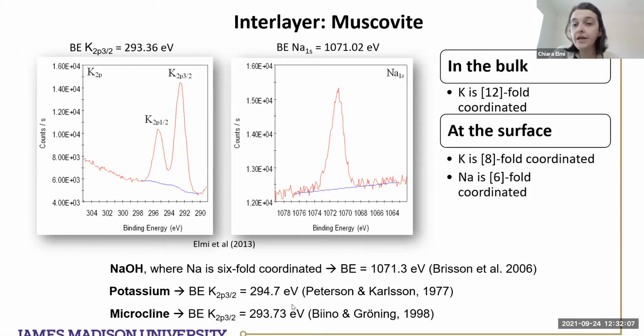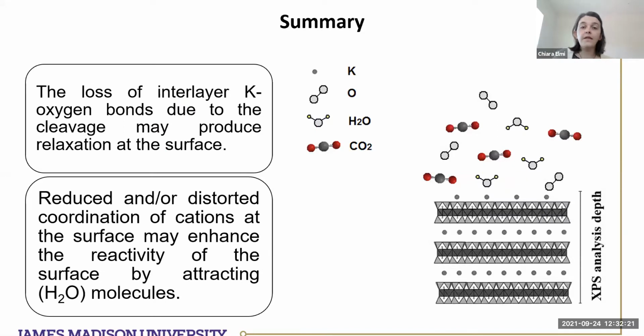That's the binding energy and the coordination that is possible to extrapolate from these peaks. And these peaks define the electron jumps in the XPS. So we relaxed the layer, and we lost some of the potassium on one side of the layer. Most of the potassium oxygen are producing this relaxation, and then this distortion in the coordination is rebalanced with the link with the CO2, oxygen, and water that is in the air and in contact with this surface.